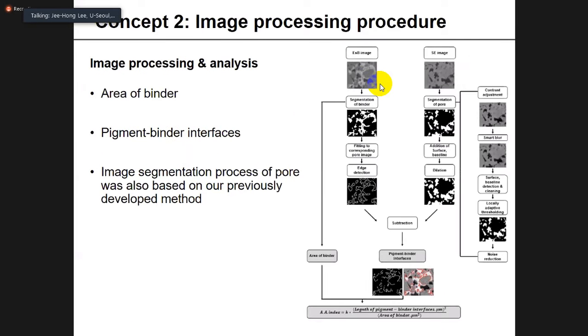So the second processing procedure can be summarized like this. As you've seen on the former page, the pigment-binder interfaces are segmented, and the area of binder can be derived from the segmentation of binder. So the AA index is also easily calculated with this method. The segmentation process of pore is also based on our previously developed method.